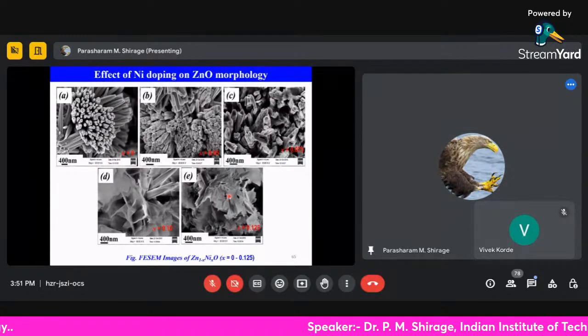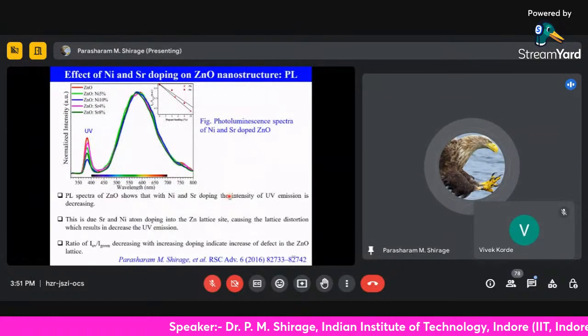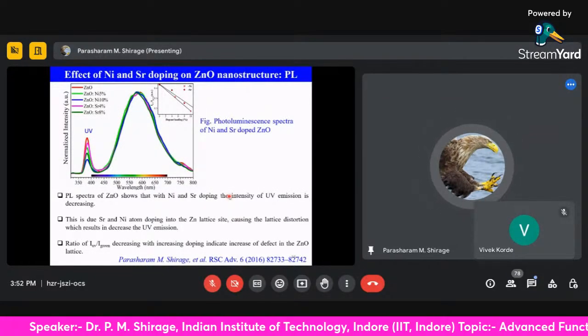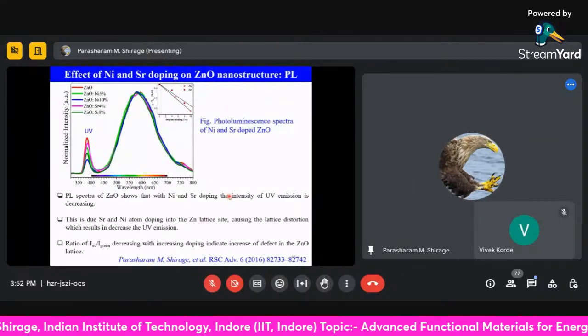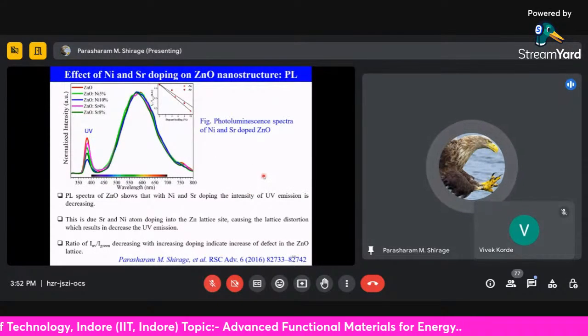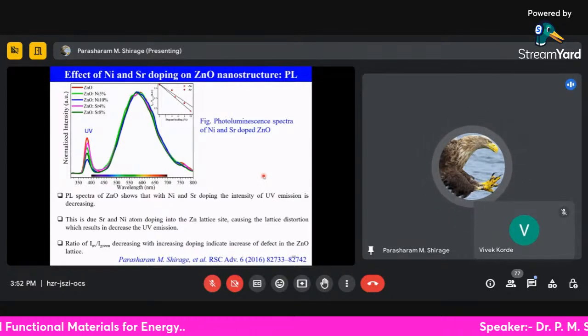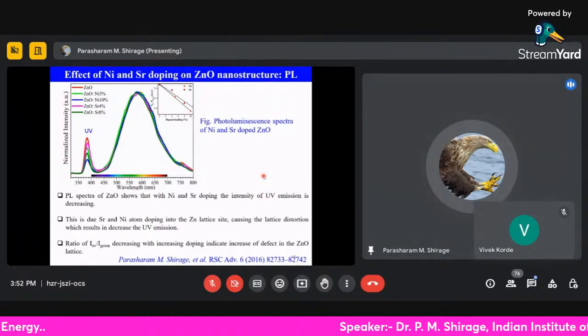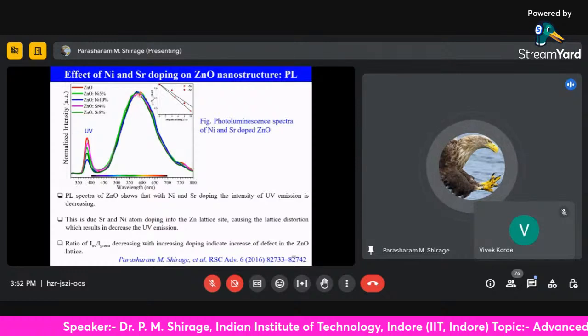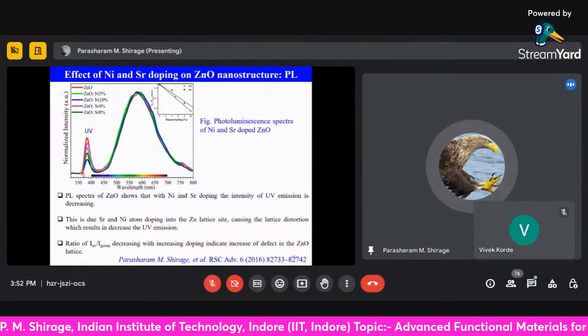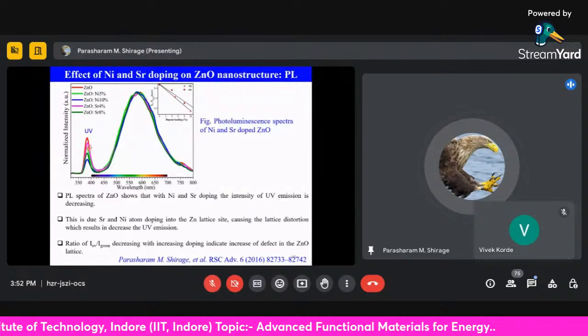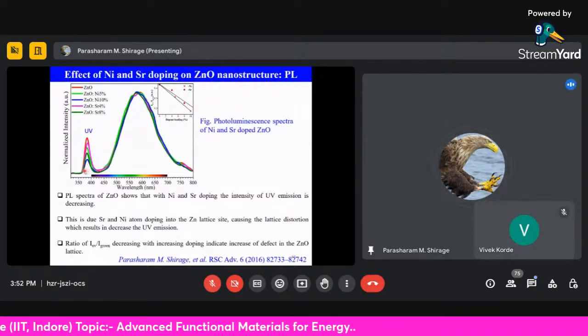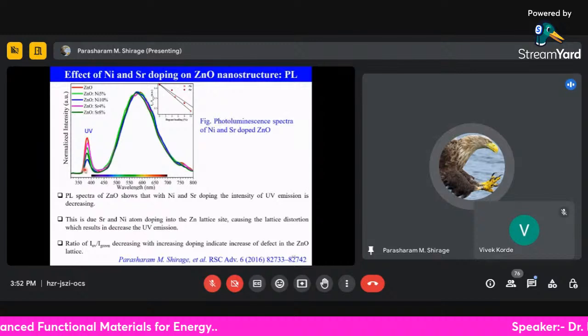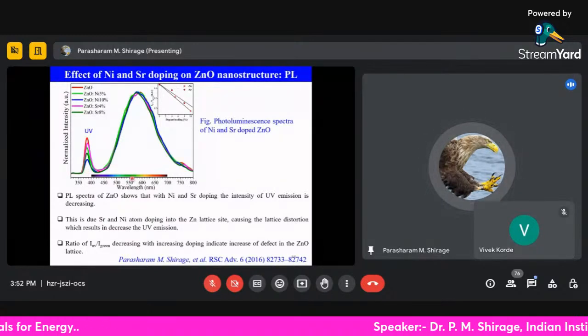Okay, now we need to study other properties, like what is the optical property of this one, what is the doping concentration, and whether that will change the optical properties. Or if the defect level is changing, that can be studied by photoluminescence studies. So if we normalize the intensity of the green light and compare the intensity of the UV light of these different doped samples, this intensity is continuously decreasing. It means that the defect concentration is changing with changing the doping of strontium and nickel. Okay, so this is very important.